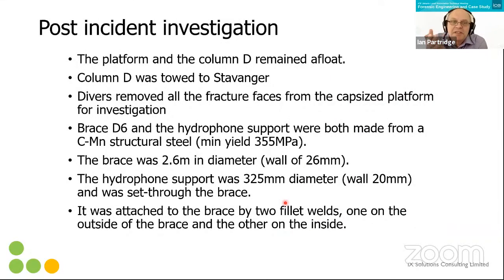So, post-incident investigation, the platform and the column that had snapped off remained afloat. They took the column to Stavanger in Norway, and divers removed the fractured faces from the capsized platform. Brace D6 is the interesting area, and it has something called a hydrophone support. It was made from a normal carbon manganese structural steel with a yield of about 355. The brace was 2.6 meters in diameter, and it was about 1 inch thick.